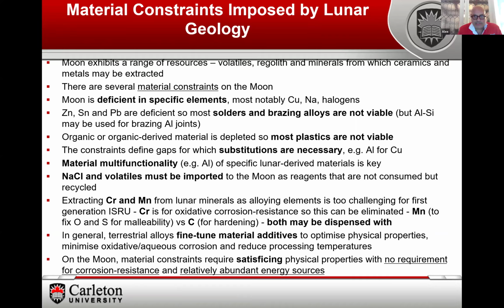What we tend to do in alloys, we tend to trade manganese against carbon for malleability and for hardening. So we can eliminate both and adjust our designs accordingly to cope with the malleability of purer metals. So in general, although in terrestrial alloys we tend to fine-tune material additives to optimize physical properties, and quite often to reduce processing temperatures, this is not an issue that we have on the moon, because as we'll see later, energy is something that we have a reasonable amount of.